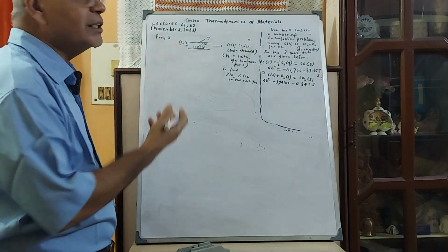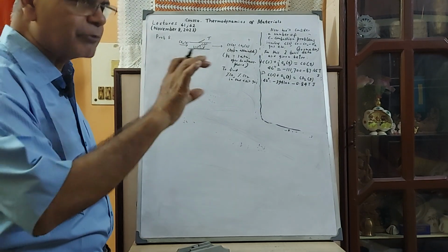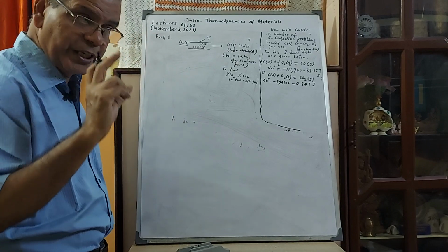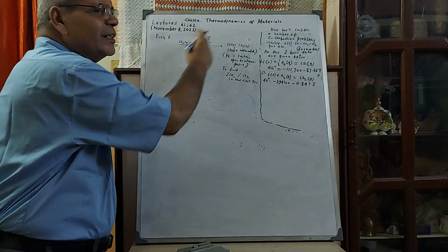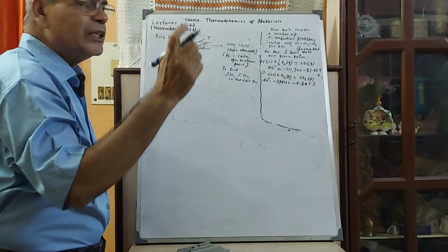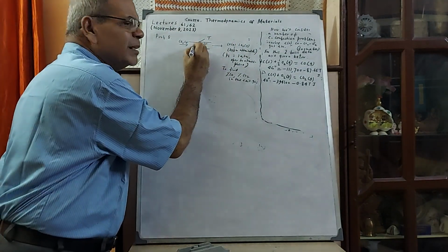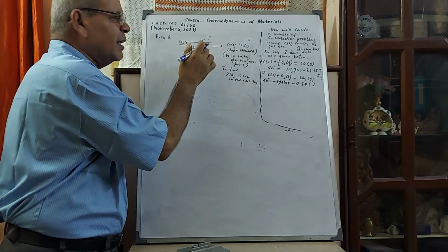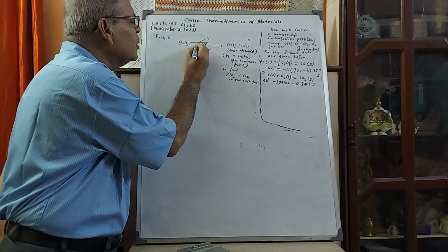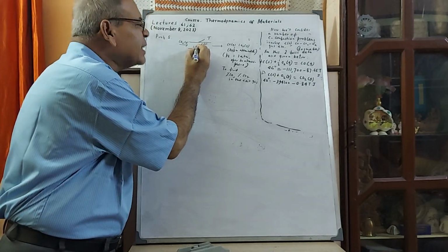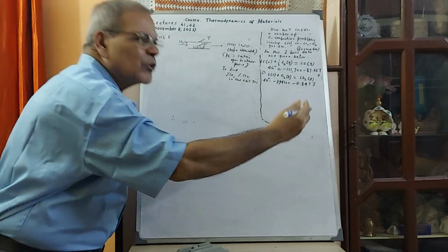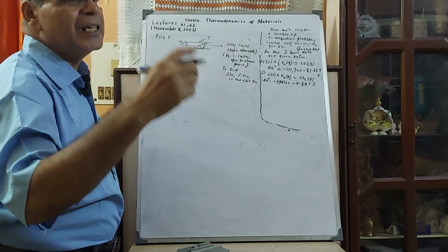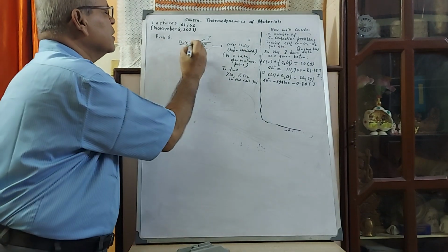That is about whose delta G0, I don't know. Whose reaction? First you have to write the reaction, then delta G of that. So you must say, sir, I must have 2 relations. One relation maybe through the equilibrium. This gas has attained equilibrium. See, where has equilibrium happened, you know? Follow this. You pretend that this is a long bed. So when the gas is flowing slowly through the carbon, and consider that at this typically high temperature, it attains equilibrium. Attaining equilibrium means it reaches the equilibrium constant.